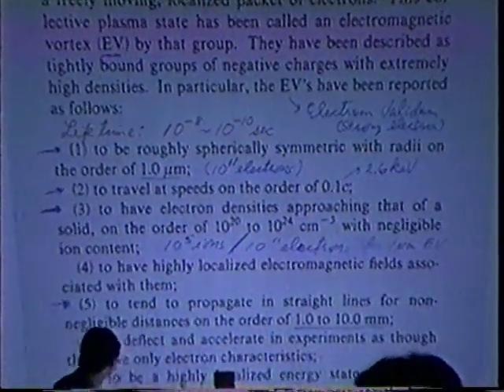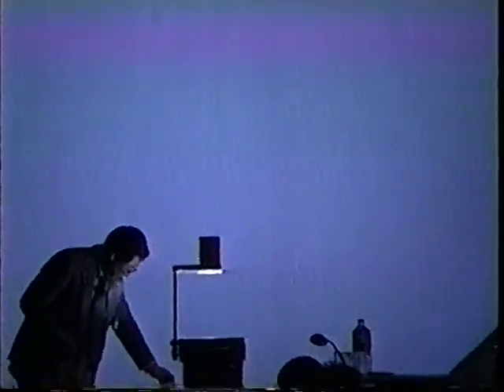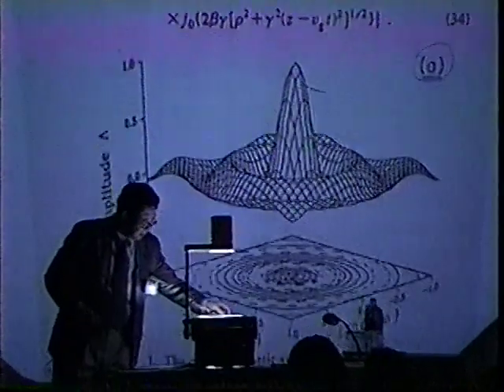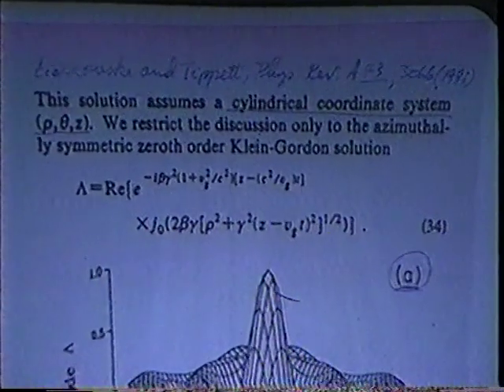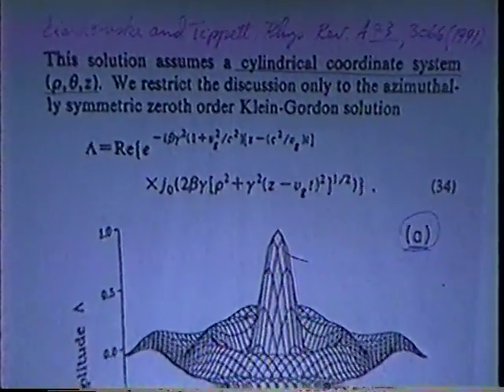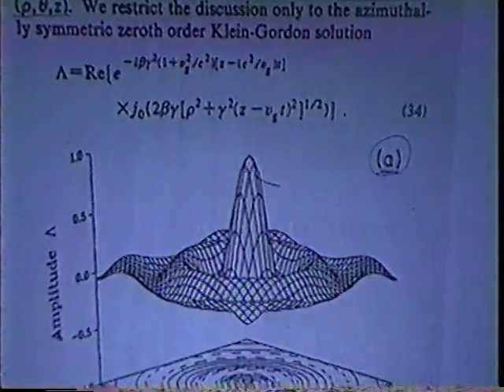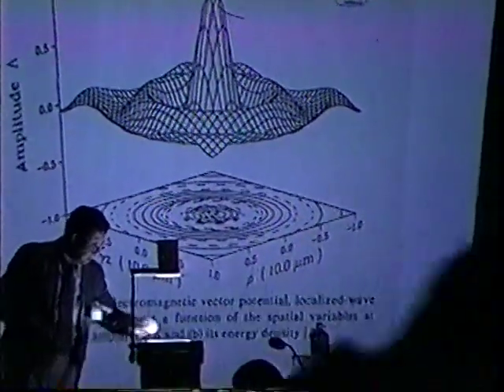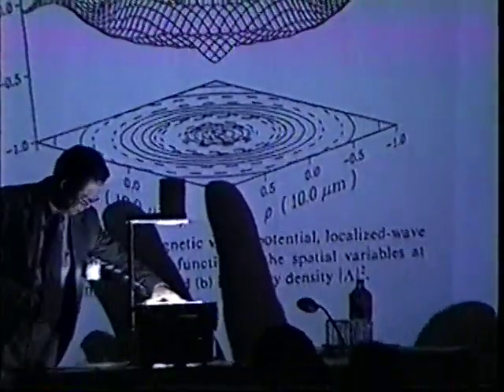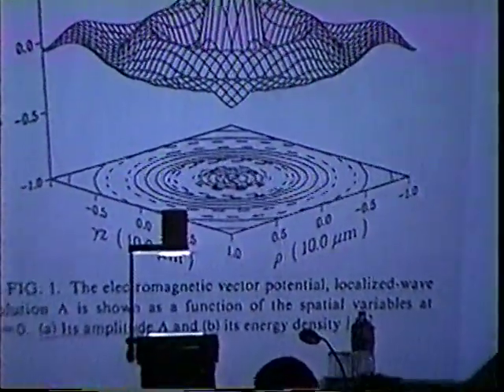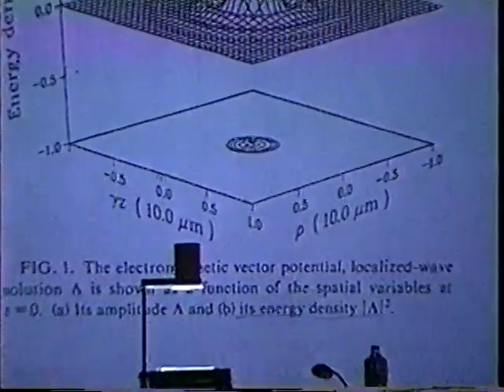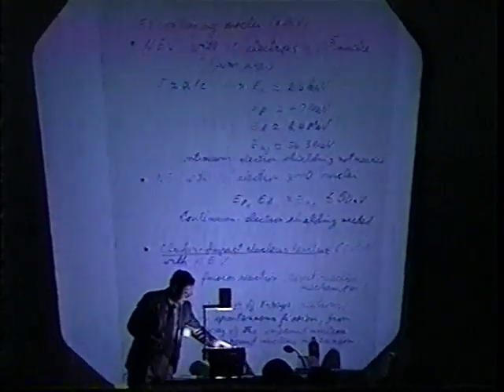Now, if this is confirmed by independent experiment, it has enormous implications for us. Incidentally, that problem was looked at by these two plasma physicists, to see whether one can obtain a solution mimicking that electron cluster by solving the Maxwell equation for plasma and recasting it in the form of the Klein-Gordon equation. And this is the solution for the amplitude. Here, the square of the amplitude looks like Ken Shoulders' electron clusters. So what this means, if it's true, is that there are theoretical justifications, but we need to confirm experimentally by independent test.